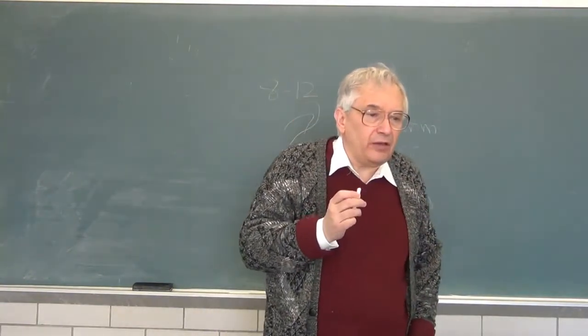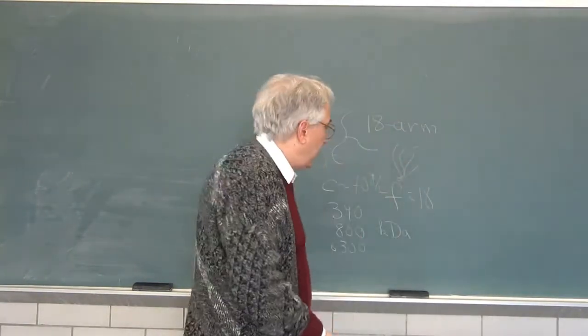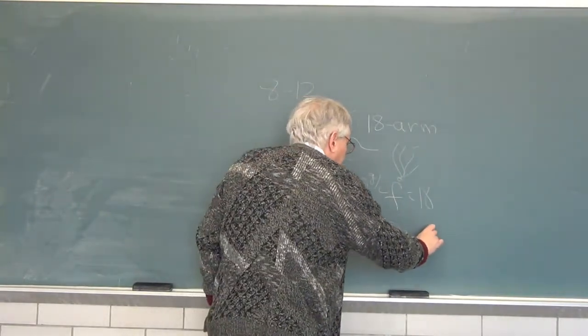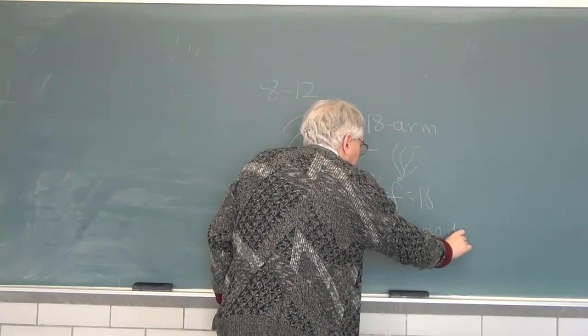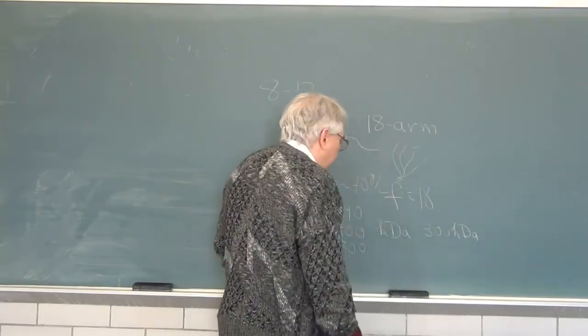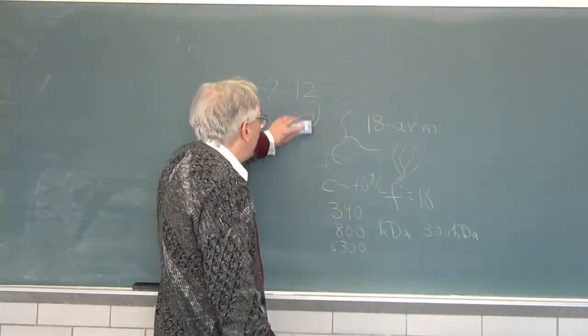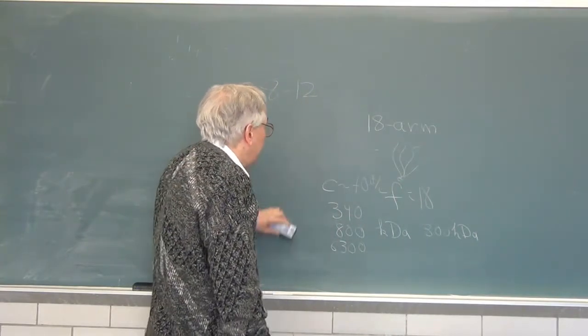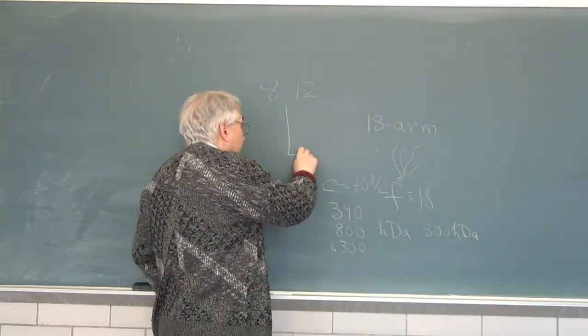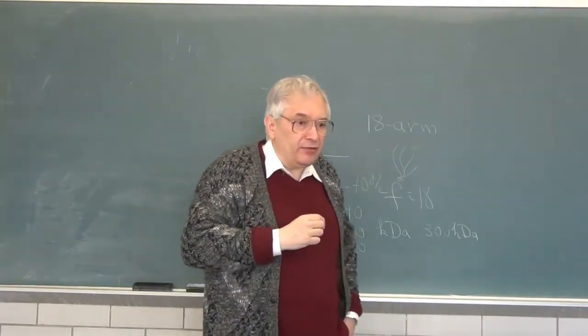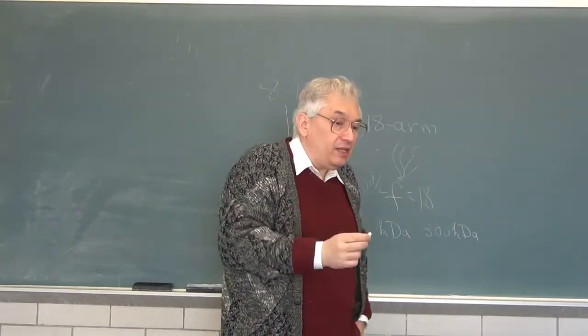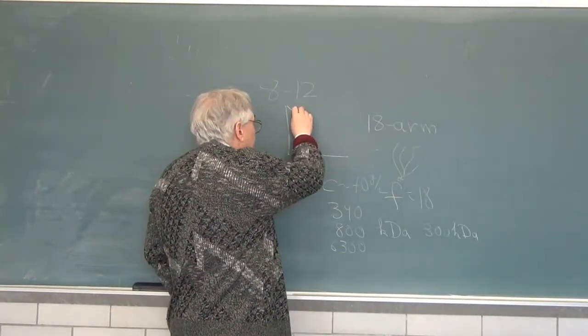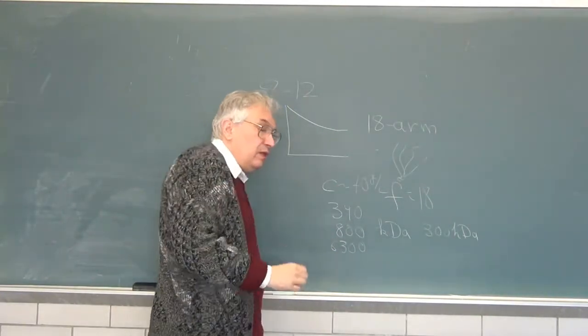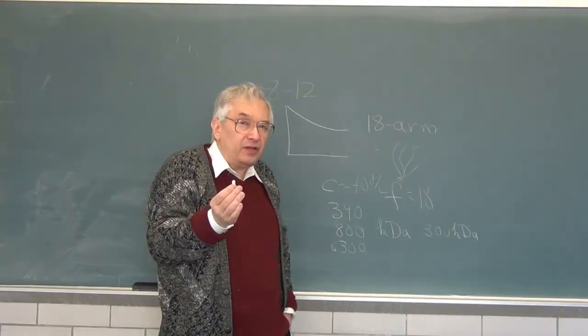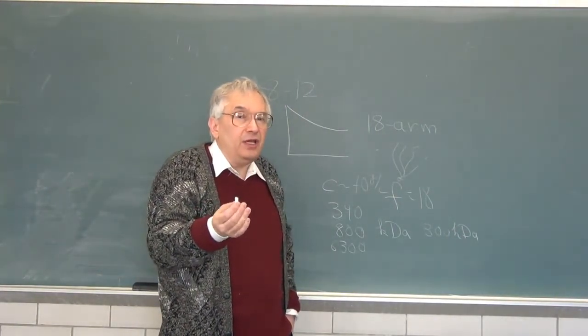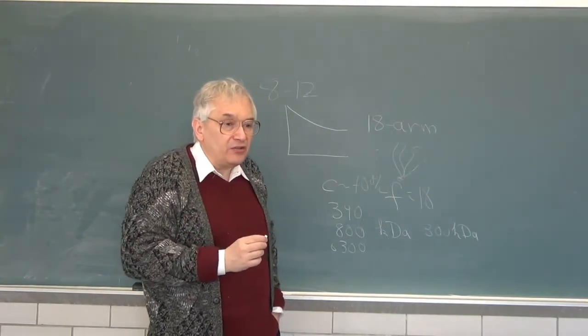And they do a comparison with a linear chain, which is a 300 kilodalton round number linear chain. So what do they see when they measure diffusion versus concentration? Well, the first answer on what they see is that as you increase the concentration, the diffusion coefficient falls. The dependence of the diffusion coefficient on polymer concentration is in fact a stretched exponential in concentration.